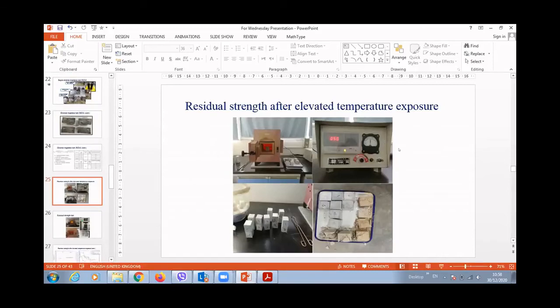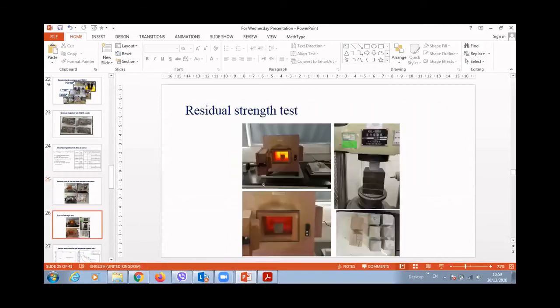The other investigation was about the residual strength after exposure to very high temperature. This picture shows the electric oven we use. Different samples were cured for more than 3 months and then put inside the oven following this protocol.